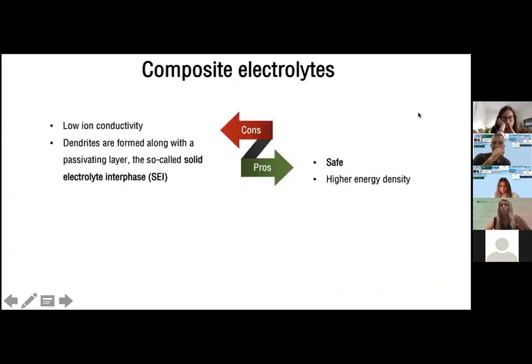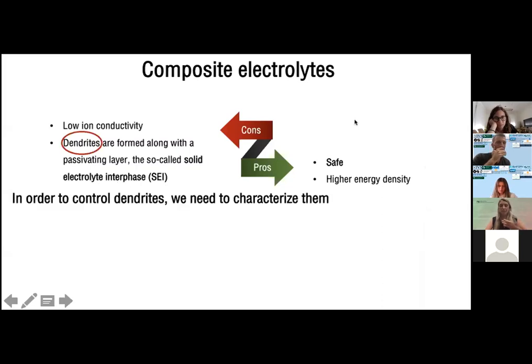As I told you, the most important advantage of composite electrolyte is that it's safe, it's non-flammable, it has higher energy density. However, we still have the problem of dendrites. Dendrites still grow, and you need to understand that it is lithium metal that can react with most of the ingredients of the composite and form a passivation layer, also known as the solid electrolyte interphase. So we still need to tackle the problem of dendrites.